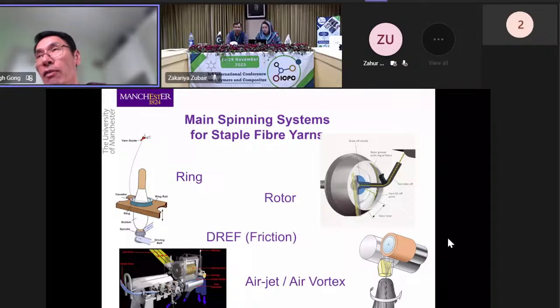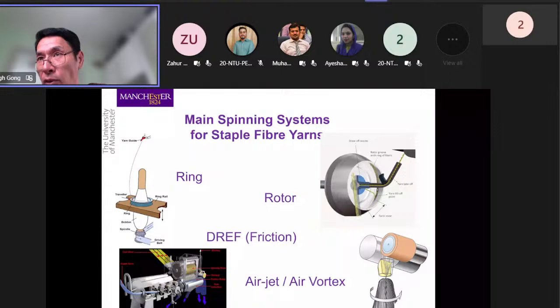So in the end, you have to turn the fibers into a yarn, suppose you manage to get all the fibers open up and draft it into the required thickness. So currently you can have ring spinning, which is very difficult to implement. And then rotor, of course, rotor is not very good dealing with dusty fibers. As I said, carbon fibers can generate lots of dust, which can cause problems. Obviously, air jet spinning is not going to work because of the way the fiber needs to be wrapping around the other fibers, and with stiffer carbon fibers, that can cause problems.